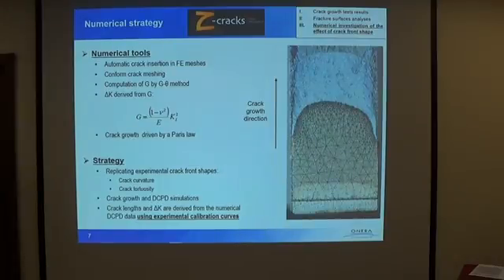The procedure we decided to use consists of replicating the exact crack front shapes from fracture surfaces under hold time conditions. This is the previous test. We will insert it into a finite element mesh and perform a crack growth simulation with a simple Paris law. During the numerical crack propagation, we will simulate the direct current potential drop technique. And ultimately, we will analyze the numerical DCPD value with the exact same assumption as per experiment, assuming a straight through-thickness crack.